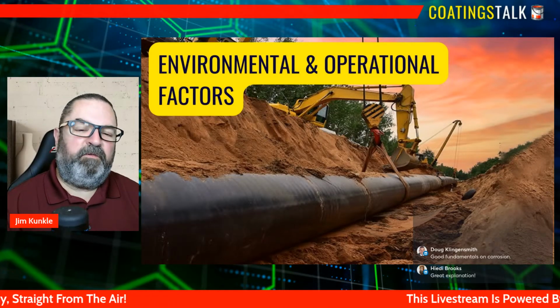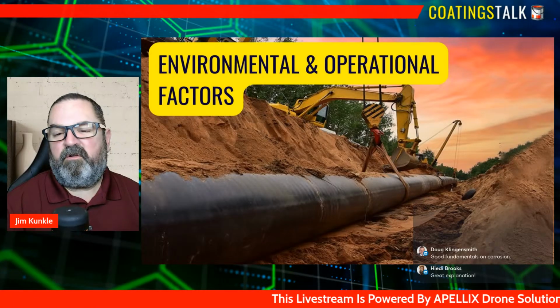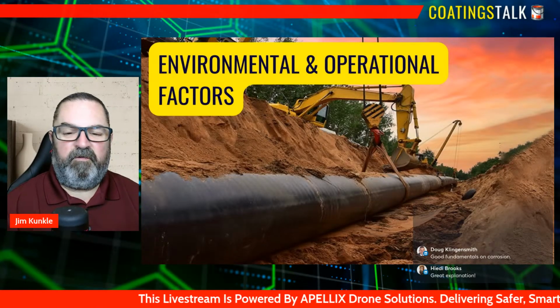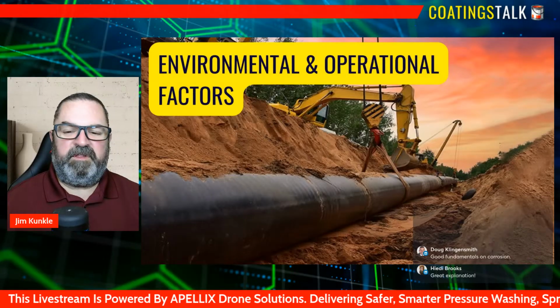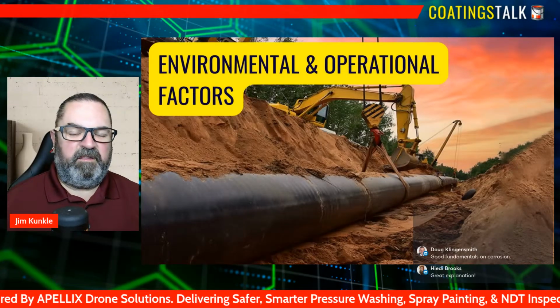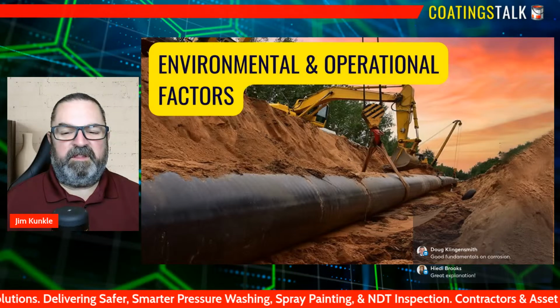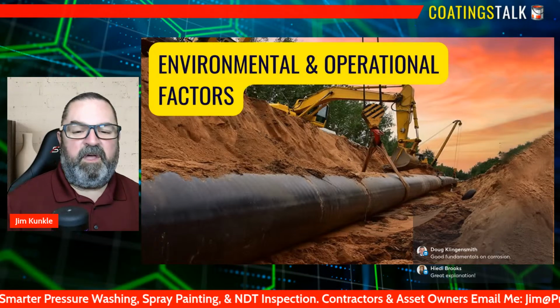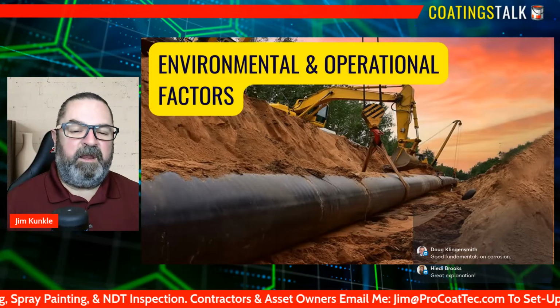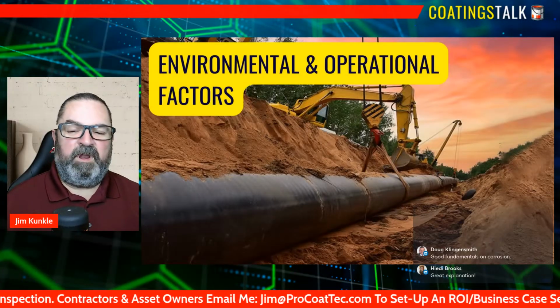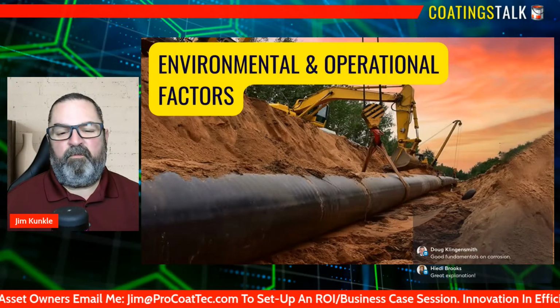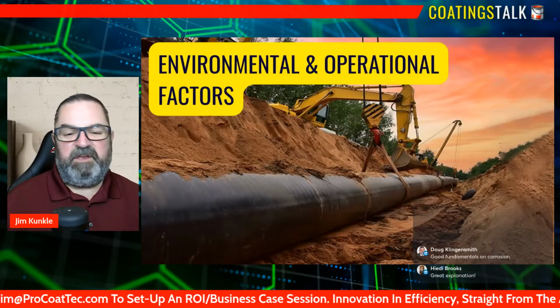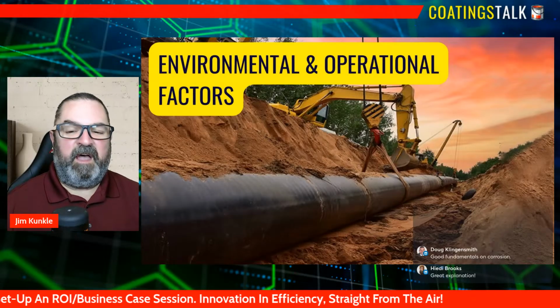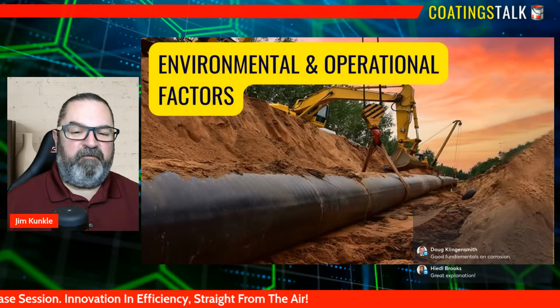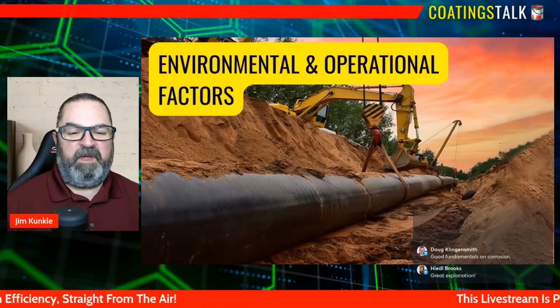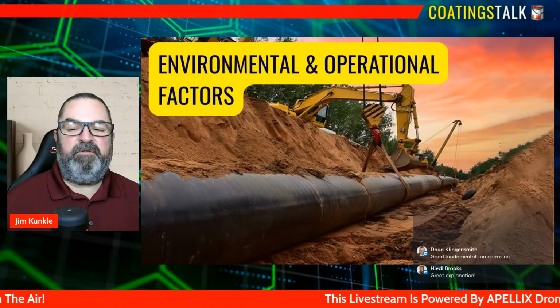So let's talk about coastal environments, because they're some of the harshest corrosion zones on the planet. And the field professionals working near the ocean, sea, and coast really see this firsthand. Salt-laden air carries chloride ions that settle on metal surfaces. They get into coatings and they can dramatically increase the conductivity of the moisture present. Even when equipment appears dry, salt can still pull moisture in from the air and keep that surface continually active, accelerating corrosion day and night. Coastal assets often show faster coating breakdown, more aggressive pitting, and higher rates of uniform corrosion compared to inland structures.